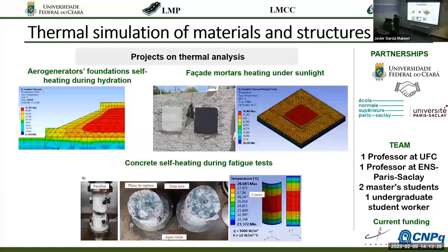Either your concrete can hydrate not very well, with delayed ettringite formation. I don't know if you are acquainted with it, but if it doesn't form in early ages, it one day will form and will crack your structure. So you should avoid high temperatures. And also you can have thermal cracking. Like you have one part of the structure that dilates and then retracts because its temperature increase was high. If you have another part that didn't have the same temperature increase because you have a huge volume, you can have a thermal crack in the first days. So two kinds of cracking that we try to predict with thermal analysis.